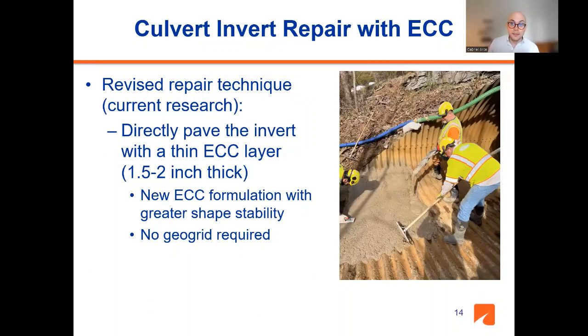Another interesting thing, we're now trying to update this repair technique to basically do the same, but without the geogrid, because the geogrid is an additional step which requires labor and cost of the material. And this revised technique, which the very first time we tested was yesterday, is the same repair, but now we use an ECC material that has greater shape stability. It's a thicker type mix. You can see the image from yesterday from the repair, and we were able to successfully repair the invert without having to use this geogrid. And hopefully in the future, I can tell you how it is performing. But so far, it has been a success.